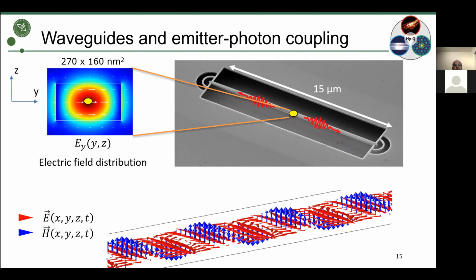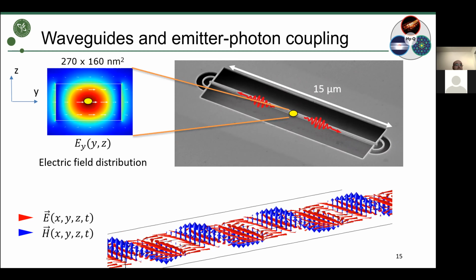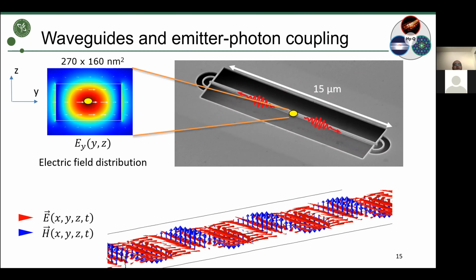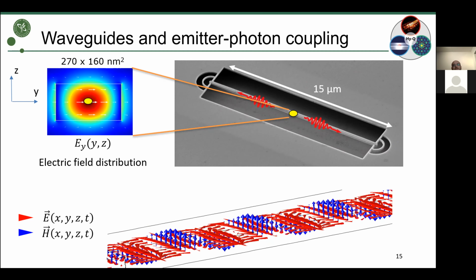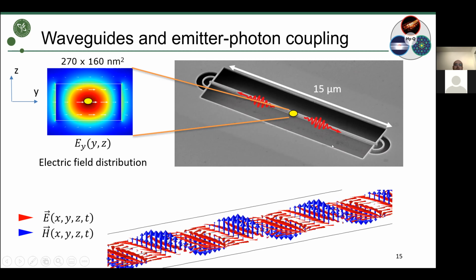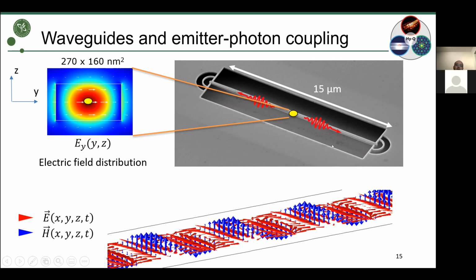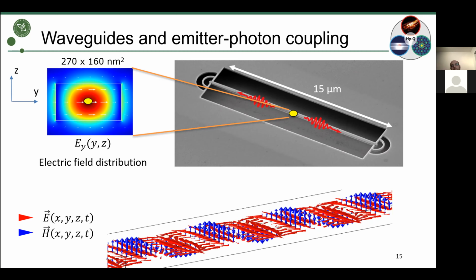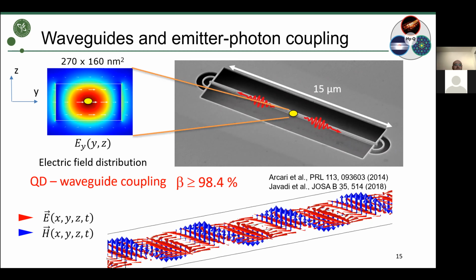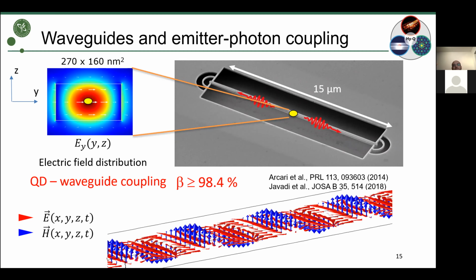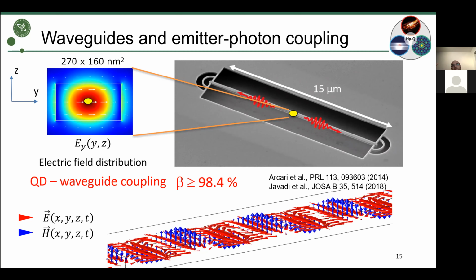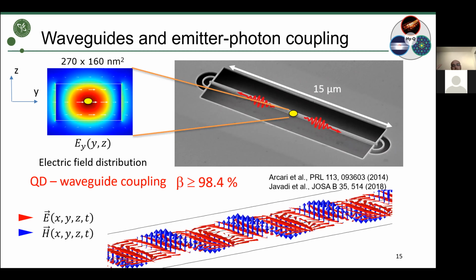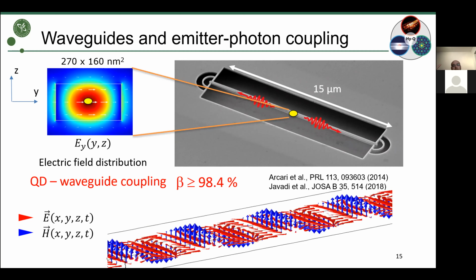And this is what I said before about the orientation of the dipole being very important, because knowing that the dipole is oriented in a particular direction allows me to orient these waveguides in such a way to maximize the coupling between the emitter and the waveguide. In fact, we can get extremely large quantum dot to waveguide coupling that is very close to unity. And this is an important result because this beta factor that you see here is a figure of merit of how deterministic my single photon source is.